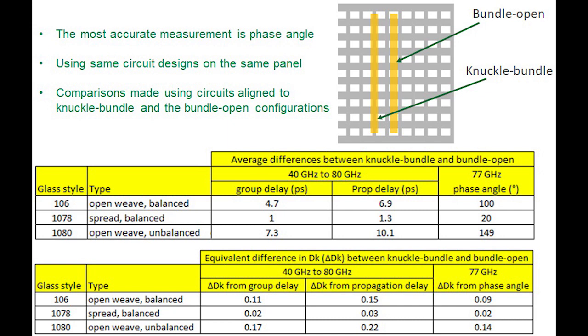The laminates were using 106, 1078, and 1080 glass. And what we were doing was we're comparing the circuit on the same panel that had the knuckle bundle orientation to the glass, and then another circuit, again on the same panel, with the bundle open configuration, and comparing the differences that we saw in group delay, propagation delay, and phase angle. I personally think phase angle is the most accurate way to look at this, so that's actually the numbers I'm going to be looking at.